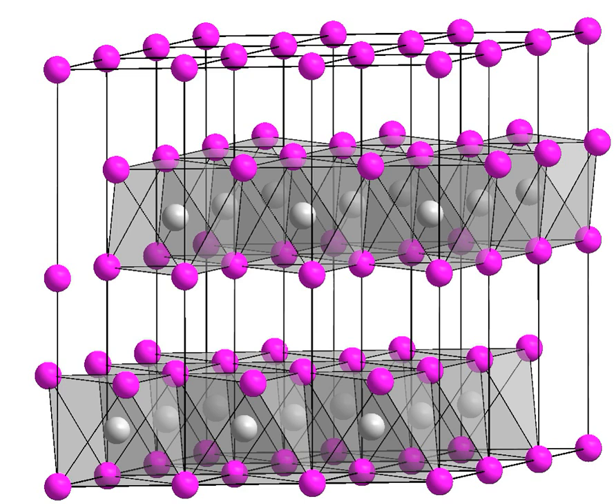Applications. The promise of titanium disulfide as a cathode material in rechargeable batteries was described in 1973 by M. Stanley Whittingham. The group 4 and 5 dichalcogenides attracted attention for their high electrical conductivities. The originally described battery used a lithium anode and a titanium disulfide cathode. This battery had high energy density and the diffusion of lithium ions into the titanium disulfide cathode was reversible, making the battery rechargeable. Titanium disulfide was chosen because it is the lightest and cheapest chalcogenide.